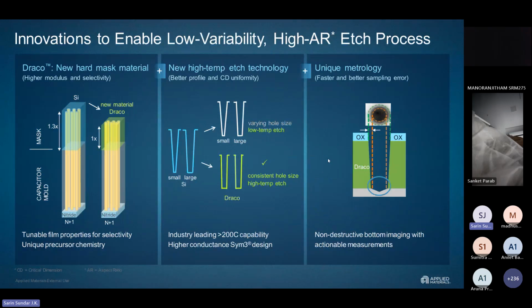Typically, what it means is if you take the Burj Khalifa tower, the tallest tower on Earth, the aspect ratio, the width to height, is 1 is to 9. So it is 9 times taller than the diameter. But here, a typical via or a hole in your NAND memory is 1 is to 500. So we have to inspect from the top. When you do an electron beam inspection from the top, you have to see whether it is tapered, whether there are defects at the bottom. It's going to be very, very challenging.